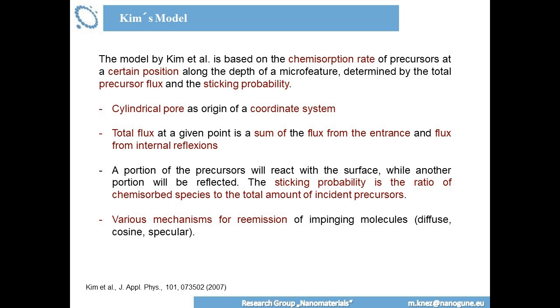How about the others? Kim's model is another approach, a different approach. It doesn't start from a pore as such and look into the entrance of the pore and the molecules diffusing into the pore, but it goes the other way around. In Kim's model, you take the pore itself as a coordinate system. And you take any point in the pore as a starting point from where you can calculate what you have there. That means what happens over time if you have a certain dose of precursor, how many of them will touch this point in the pore, and how many of them will stick to this area.